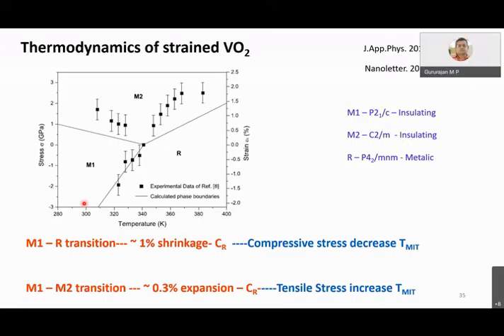Right. So in fact, it's very interesting, this kind of stress-temperature phase diagram, starting from 2010 and so on. Already it is published in a few papers. As I said earlier, the room temperature phase is the monoclinic M1 phase. I have mentioned the space group for your reference. And I'm talking about thermally induced phase transformation going from monoclinic to rutile or the tetragonal phase, right? In the absence of any strain or stress, the phase transformation temperature is around 68 degrees Celsius.